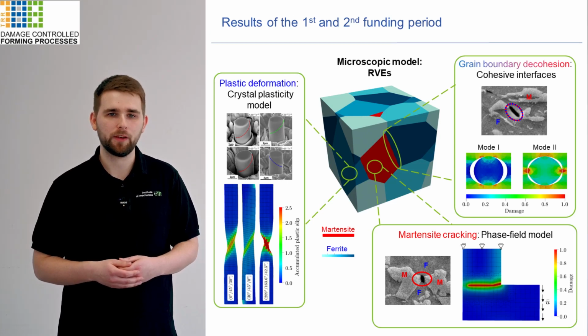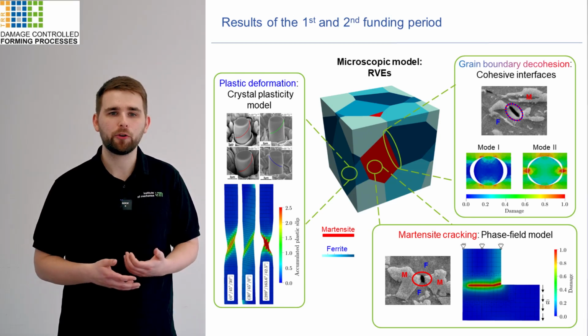different algorithmic schemes. The two main damage mechanisms identified by other projects dealing with characterization are grain boundary decohesion at interfaces and microcracks within the quasi-brittle martensite, leading to void nucleation and growth.